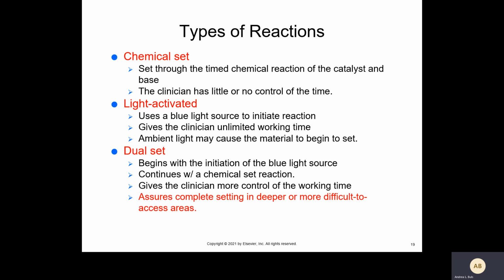One area that dual set is very helpful is veneers. If we are cementing those with a resin that must be cured, we are going to be light curing through the veneer, and we want the chemical to also cause curing so that underneath that veneer, we're sure that we're getting a solid and complete set. Same like under ortho brackets. We can cure around the edges, but we want to make sure that it's cured all the way through. So a dual set is ideal for both of those applications.